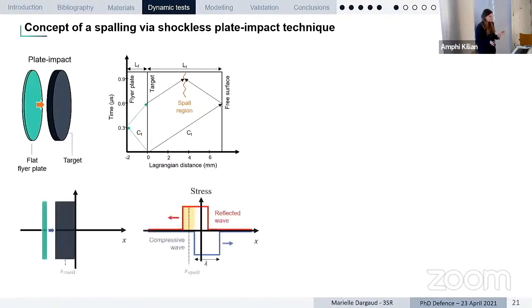In the classical configuration, there is one main limitation: this flat contact is going to generate a compressive wave which has a rectangular shape, because we have a jump of stress upon impact due to this flat contact. The idea here is to be able to control the loading rate during this test. To do this, we need to avoid this rectangular shape for the compressive pulse.